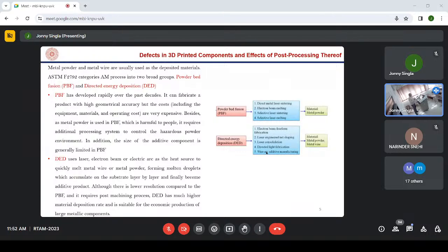PBF has developed rapidly over the past decades. It can fabricate a product with high geometrical accuracy, but the costs are on the higher side. Besides, as metal powder is used in PBF, which is harmful to people, it requires an additional processing system to control the hazardous powder environment. In addition, the size of the additive component is generally limited in PBF.